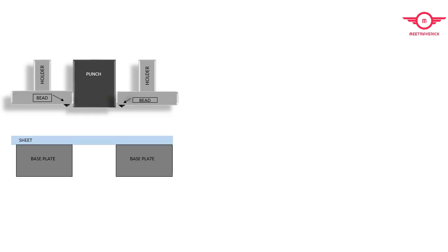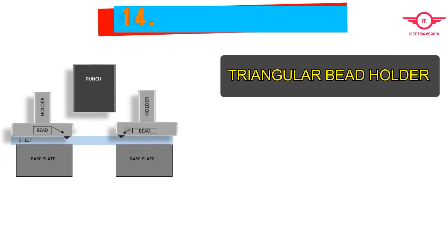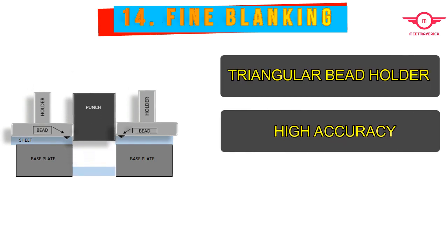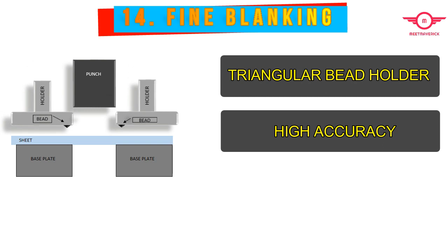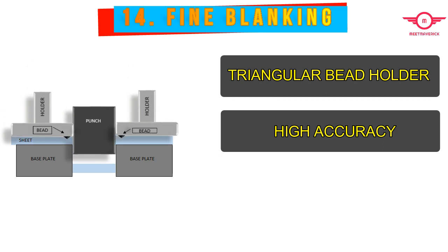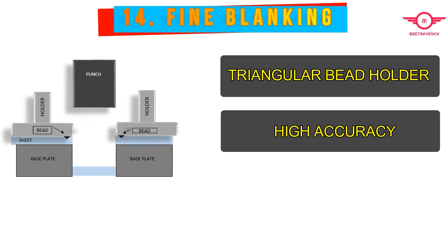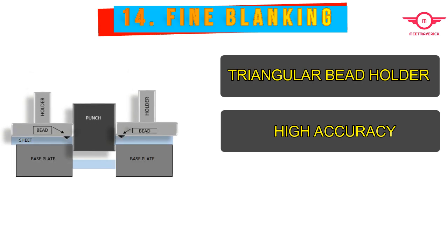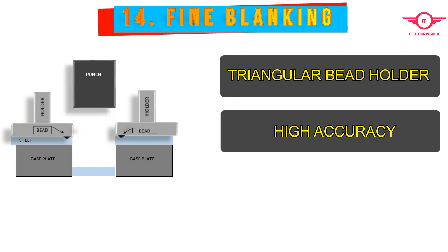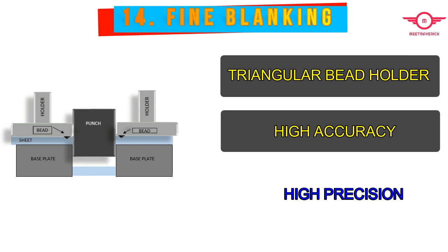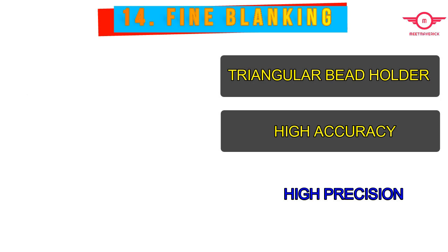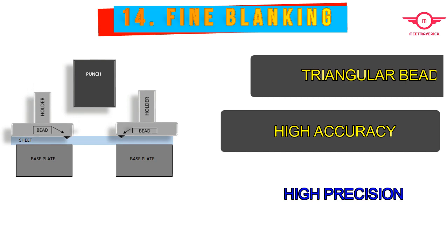Fine blanking. Fine blanking is a precision blanking method in which a powerful sheet holder having a triangular projection bead immediately adjacent to the punch face is on the side which presses down on the sheet. It is used to generate a high compressive stress at the shear faces, resulting in clean shear faces. During blanking, a cushion firmly supports the blank from the opposite side to minimize burring. Chips are produced in this process.